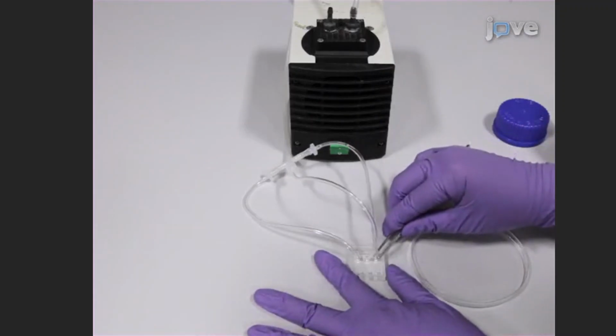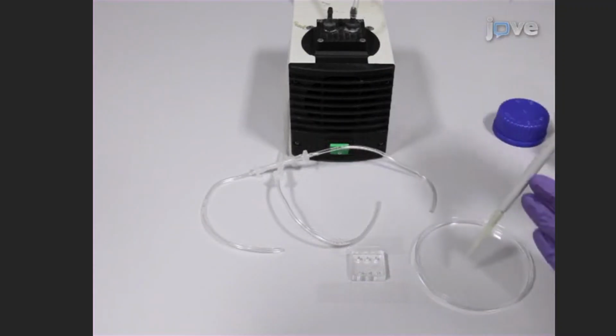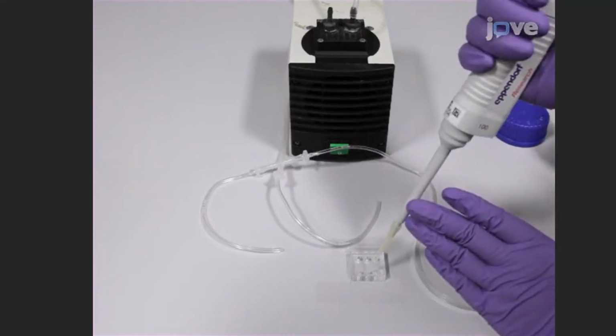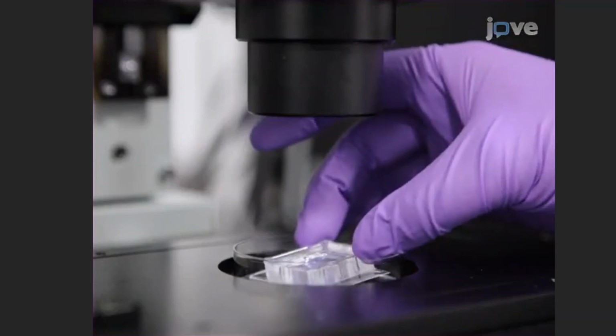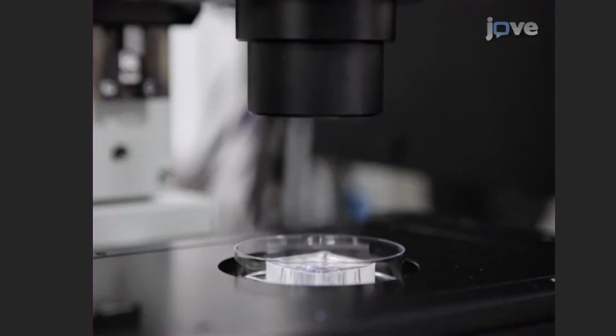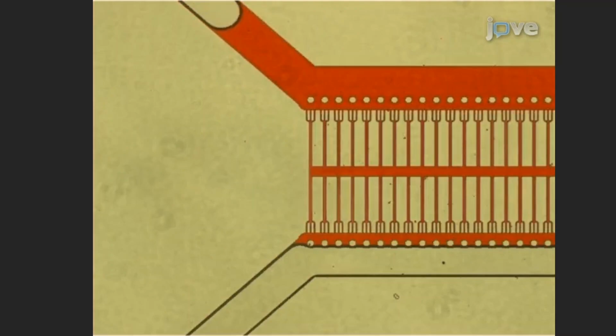Subsequently, detach the tubing and remove any remaining PBS from the ports. Transfer the device to a microscope and heat using illumination to increase evaporation from the ports for rapid water mask formation. Inspect the device by microscopy to ensure water masking is complete.